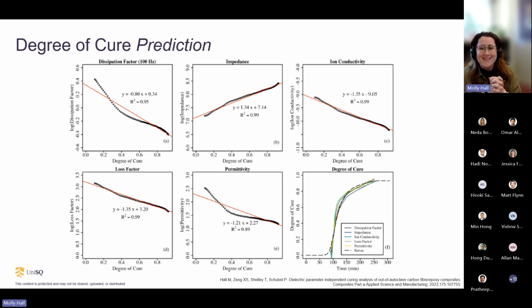The word prediction on this slide might be a little bit hopeful, but there's another method for determining the degree of cure progression that was proposed out of a research group in the UK. And for this technique, they really focused on the impedance only. So again, we were looking at this method for, is it parameter independent? But this technique, they correlated the degree of cure progression with the dielectric signal and determined that there's a pretty good linear correlation there. And they used that equation to then go predict your degree of cure over the rest of the range. And this worked quite well for the rest of the parameters.